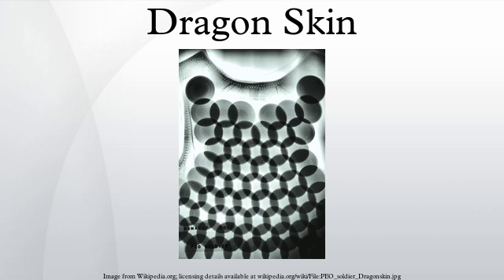Dragon Skin Level 3 armor was also tested the week of October 2, 2006 by Dr. Gary Roberts, DDS, Stanford University Medical Center. These tests were conducted for a local law enforcement agency. As a control sample, a stand-alone armored Mobility Inc. Level 3 steel composite plate armor was used for comparison. Both types of armor were conditioned for 12 hours at 170 degrees Fahrenheit, then moved to ambient air for approximately 90 minutes prior to being shot.